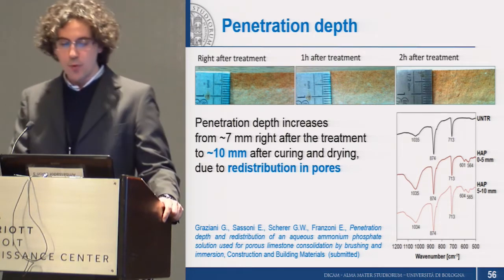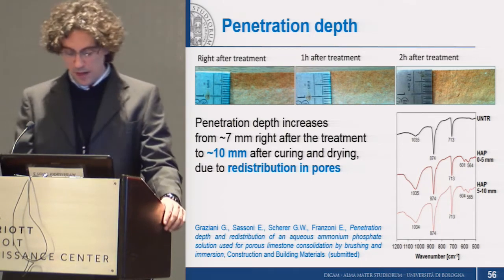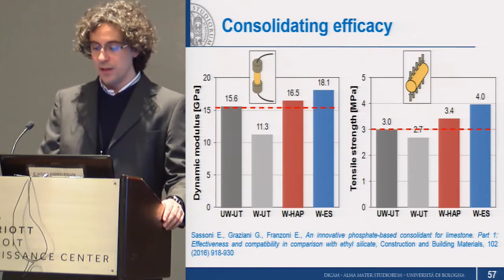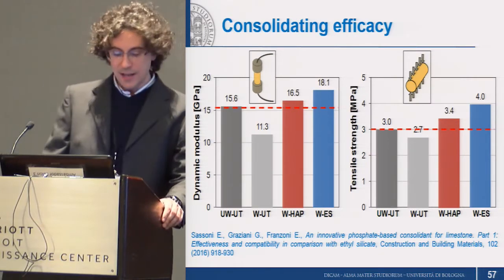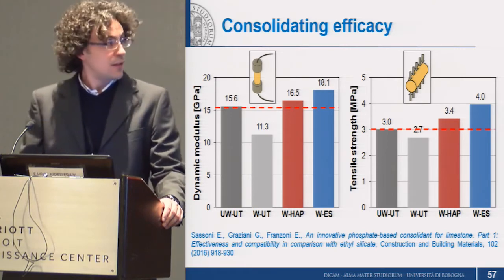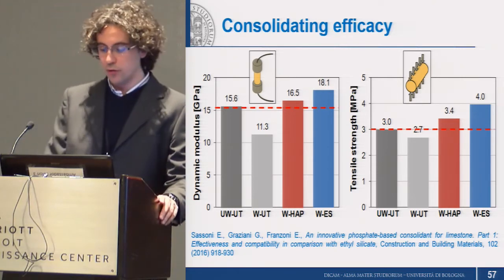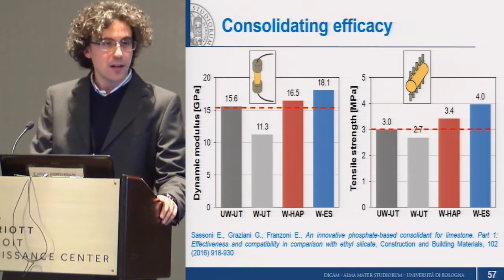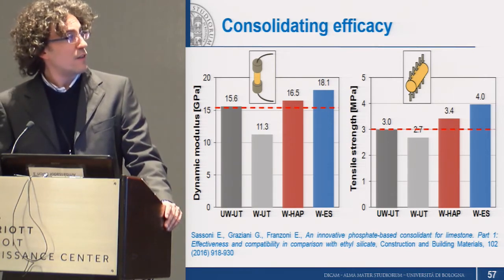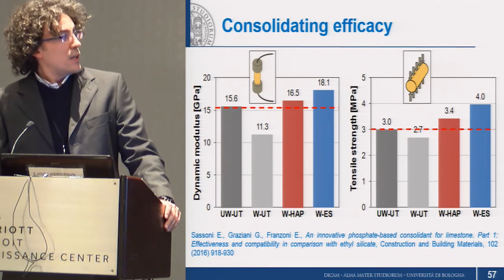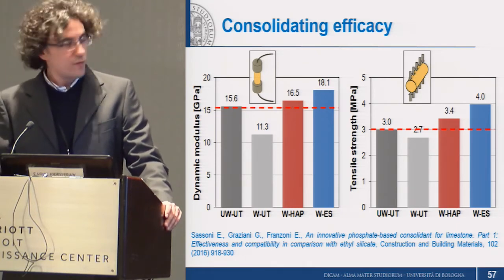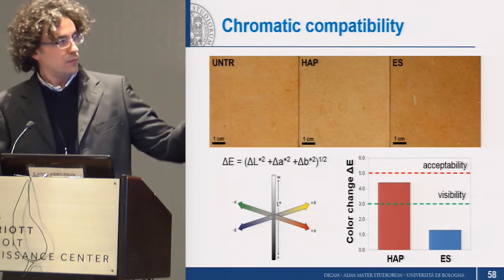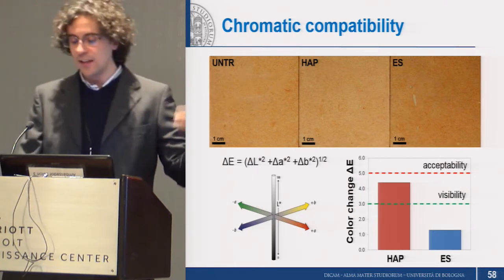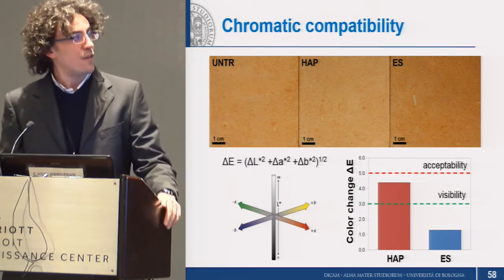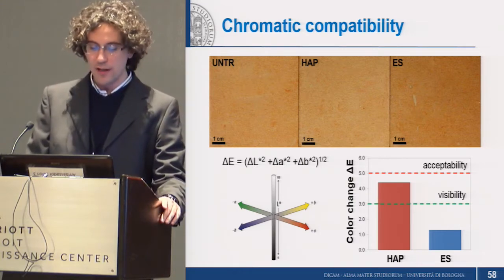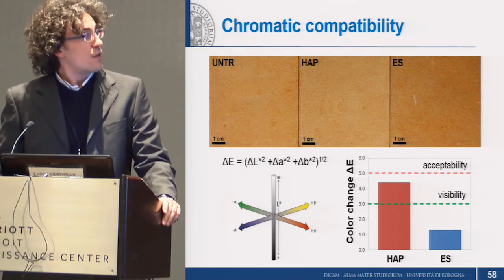In terms of mechanical properties, which we measured by ultrasounds and by tensile splitting tests, and also in comparison with ethyl silicate, which is the most widely used consolidant in the field, we were able to reestablish the original mechanical properties, as I mentioned before in the case of marble. We didn't cause any dramatic color change, which of course is positive, because although slightly detectable by the human eye, the color difference is still below the threshold that I mentioned for conservation treatments.